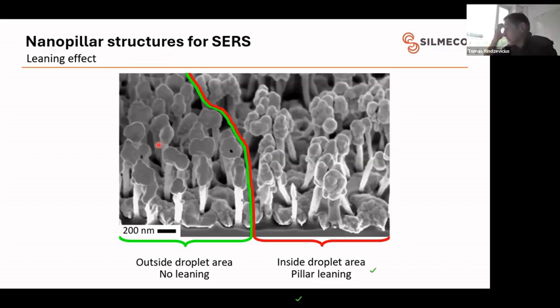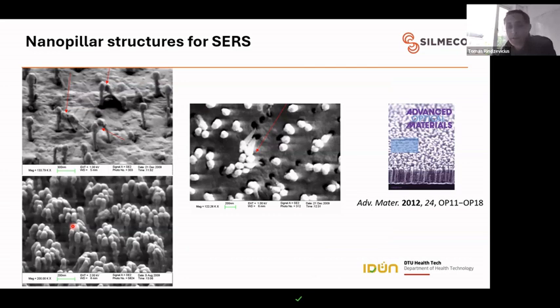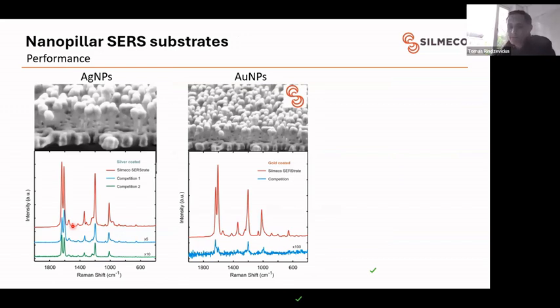And then if you look at the scanning electron microscopy, outside the droplet area, the pillars are standing. Inside the droplet area, you can see these small clusters being created as a result of the droplet drying, where capillary forces pull the pillars together. And this is how it all started. We tested these structures with some basic molecules, and it was simple to fabricate. Then the main work was done by Michael Schmidt from Anja Boysen's group. And the first comparison that we did was against a substrate that we found on the market back in the day, like 8 years ago or so, for droplet deposition, because that is important, how you deposit your analyte. For droplet deposition, it seemed like a good substrate, at least compared to the competition that we could find.